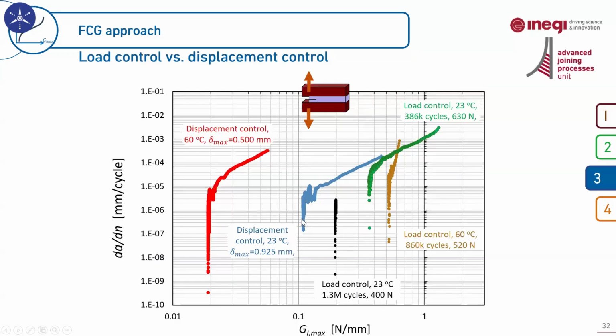No big difference, I would say, but when we increased the temperature to 60 C and we repeated this test, load control and displacement control, we see here that actually the difference between the threshold energy of load and displacement control, both of them are actually even more than room temperature. But the good point here is that for both cases of load control and displacement control, the M values were similar. And so in case that we perform a test under load control or displacement control, probably M would be the same for both approaches, but threshold might be different. And we need to be very careful, especially if you design the joints based on safe life philosophy.